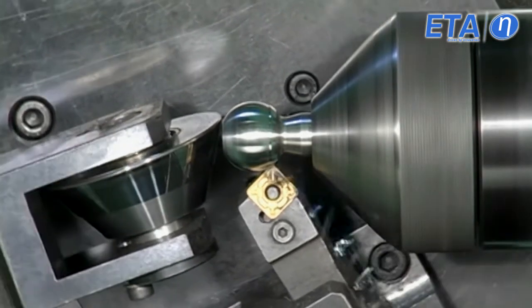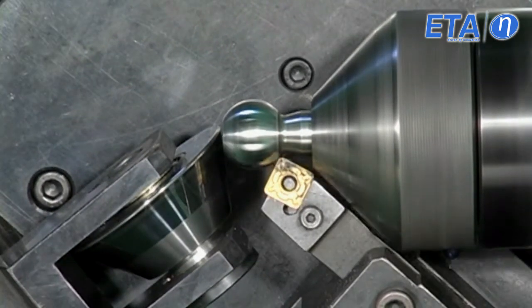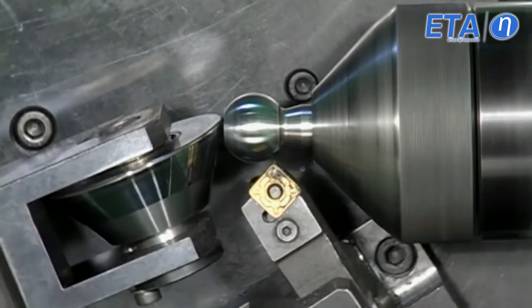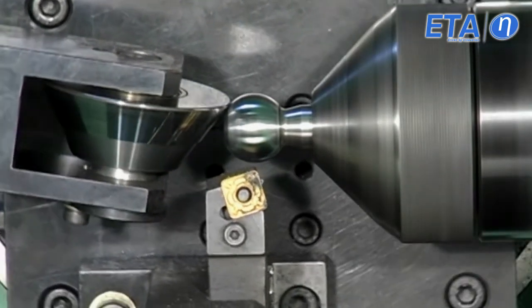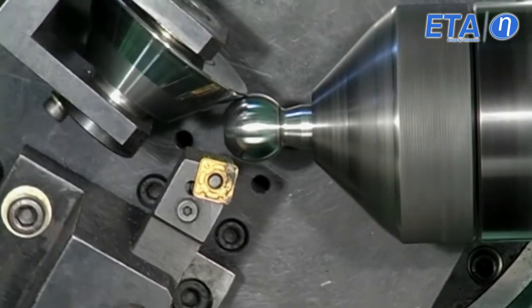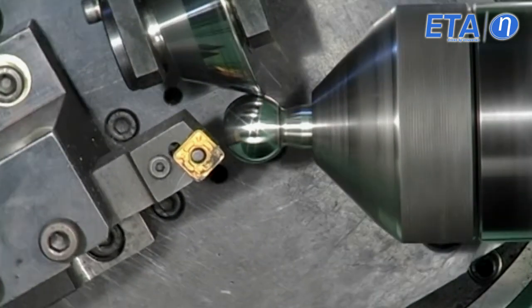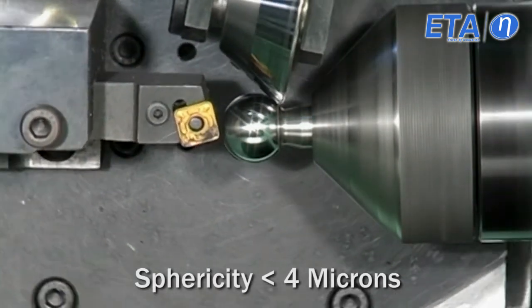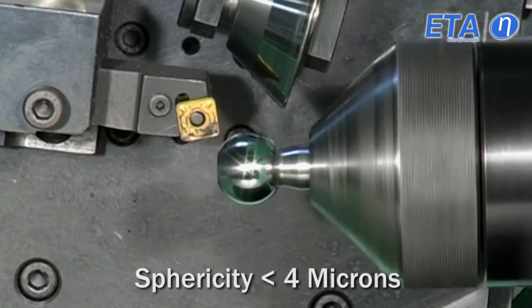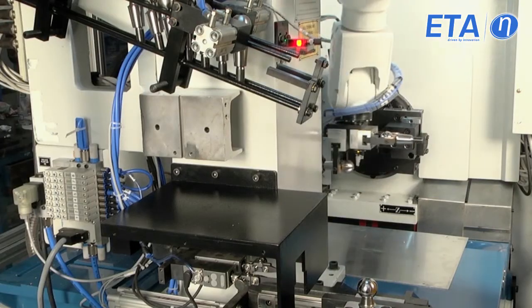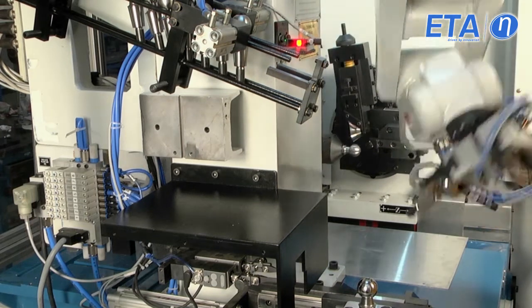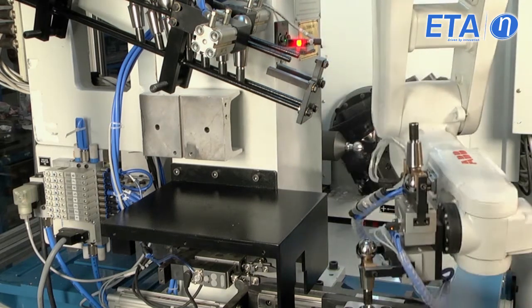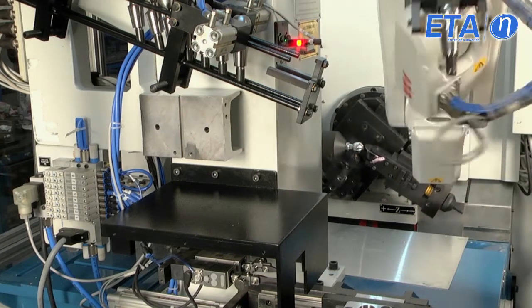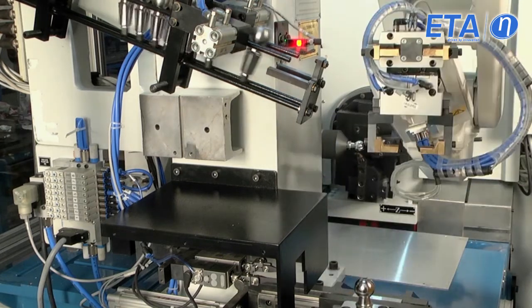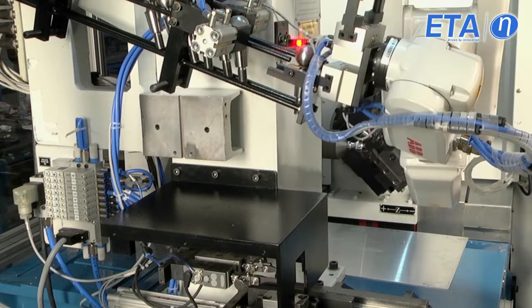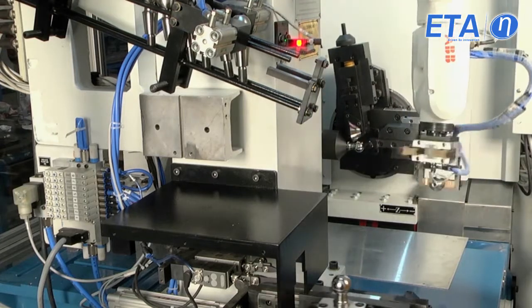Auto calibration facility using a 0.1 micron accuracy Marpose gauge facilitates adjustment of the tool tip automatically for tool compensation in a closed loop control. The sphericity achieved is within 4 microns and surface finish better than 0.1 micron raw value. The machine can be tooled up for IBJ, OBJ and SPJ ball pins. ETA BT-BMS are totally unmanned during operations.